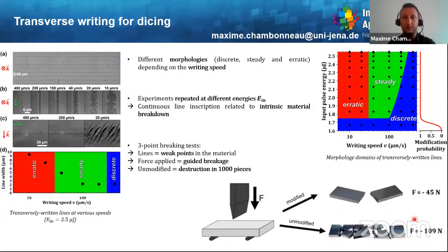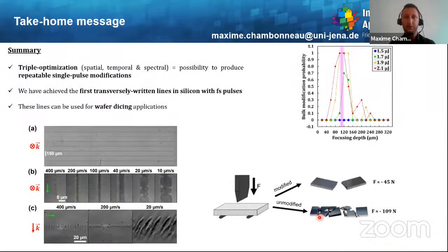In comparison, when the wafer is not modified and you apply some pressure on the wafer, then it is destroyed in 1,000 pieces. So here is the take-home message for this last part. By using a triple optimization in the spatial, temporal, and spectral domain, we were able to produce some repeatable single pulse modifications. We have also achieved the very first transversely written lines inside silicon with femtosecond laser pulses, and those lines can be used for wafer dicing applications.